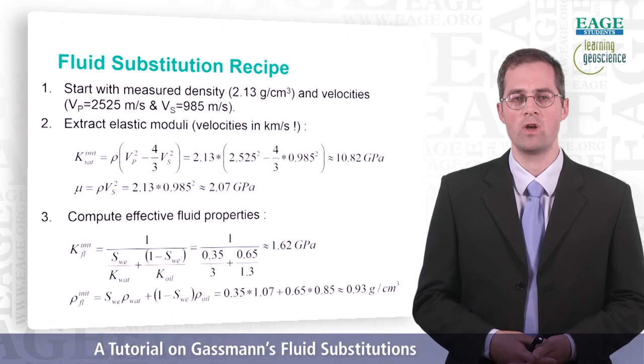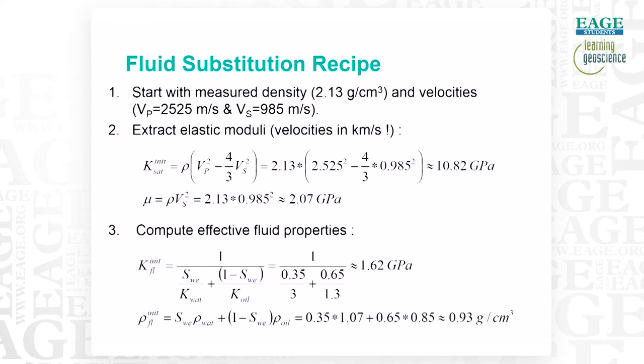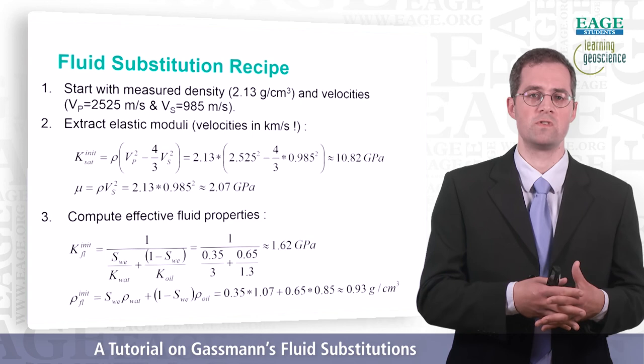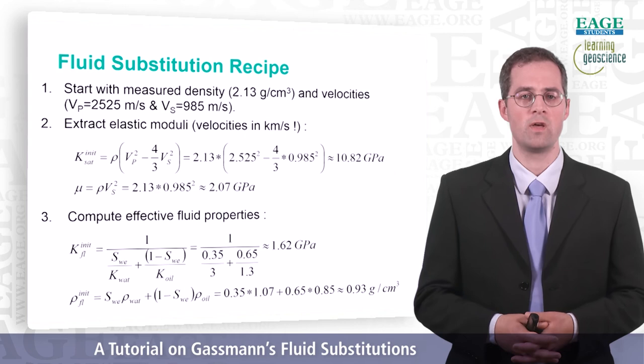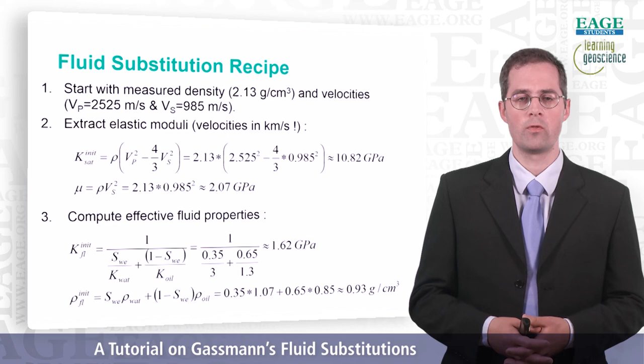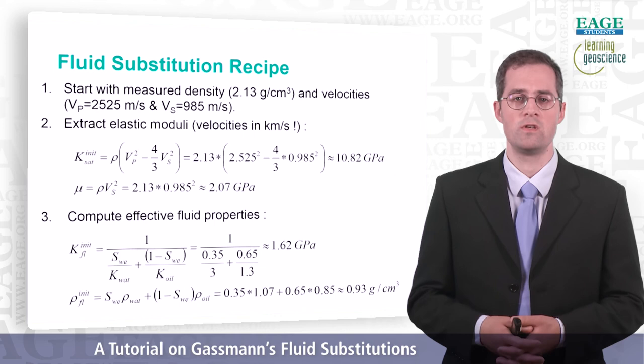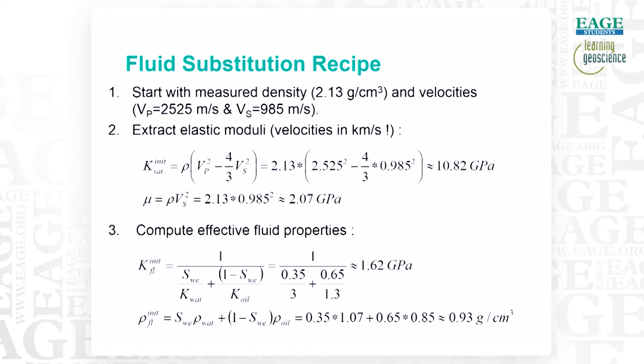It's just the product of density multiplied by square the S wave velocity, and we have around 2 gigapascal in that case. Then obviously we need to compute the effective fluid properties, because we know the oil properties and the water properties, but actually we have a mixture of both oil and water with a water saturation of 35% and hence an oil saturation of 65%. So we will assume that they are perfectly mixed at the finer scale, and in that case we can use the formula that I described previously. For the bulk modulus of the effective fluid, we can use the Reuss average, and this will give us a bulk modulus of 1.62 gigapascal. And for the density, it's even easier, we just use an arithmetic mean, which in the end gives us 0.93 grams per cubic centimeter.